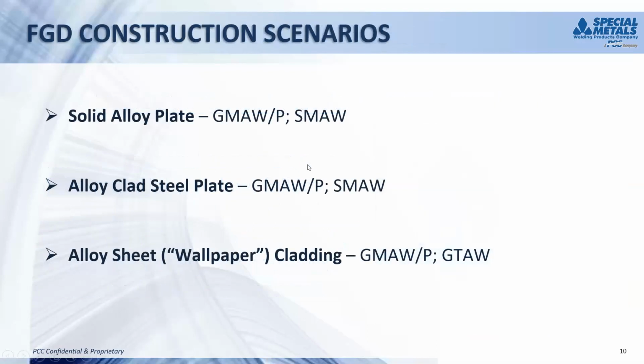The next slide. There's been basically 3 types of construction that are used for building FGD equipment utilizing nickel-based alloys. They can be solid alloy plate. In that case, welding would usually be done by either shielded metal arc welding or gas metal arc welding in the pulse mode of transfer. A way to reduce costs is to use alloy clad steel plate. And in this case, the steel part of the clad plate acts as the structural member of the system, and the alloy cladding, which is typically maybe 1.6 millimeters thick, protects the structure from the aggressive corrosive environment inside the system.